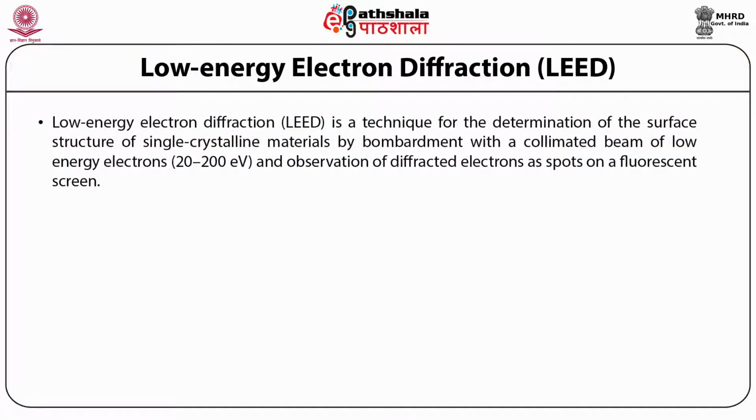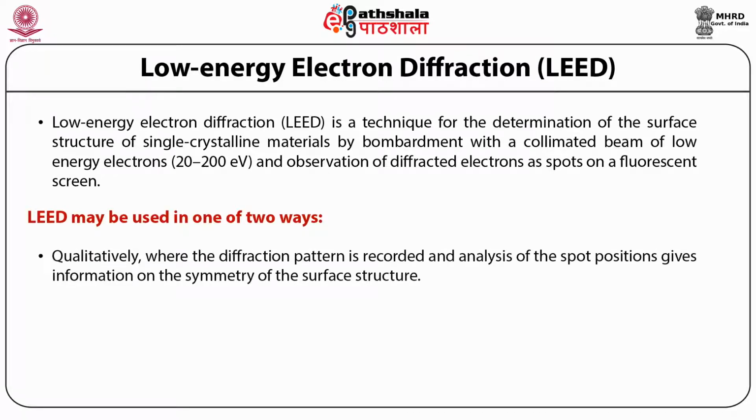Low energy electron diffraction is a technique for determination of the surface structure of single crystalline material by bombardment with a collimated beam of low energy electrons, 20 to 200 electron volts, and observation of diffracted electrons as spots on a fluorescent screen. LEED may be used in one of two ways: qualitatively, where the diffraction pattern is recorded and analysis of the spot positions gives information on the symmetry of the surface structure.